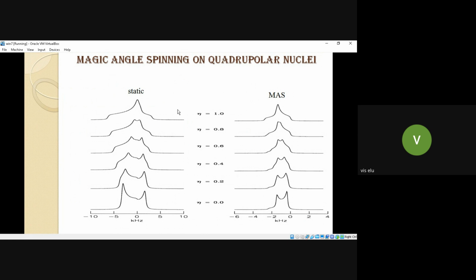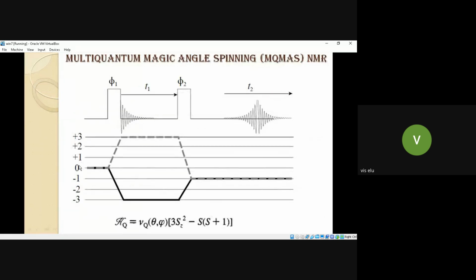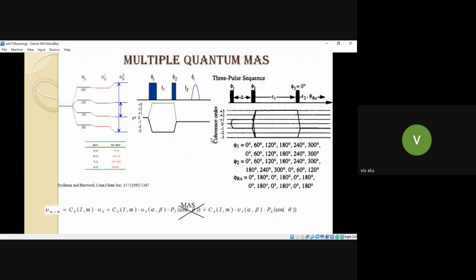In a static spectrum, you can see that the spectrum is a distribution. Even if you put magic angle spinning, your resolution will not happen. It means the spectral editing is not happening. Why is it not happening? I'm putting all my energy into magic angle experiments, and I'm not resolving. Why are you not resolving? Because you have a quadrupolar interaction inside. So that has to be dealt with in a separate, very different way, because your nuclear separation is different. You see that it has a spin of 3/2, so you will have a different axial orientation. Here is +3/2, +1/2, -1/2, -3/2. So this is the energy level separation.